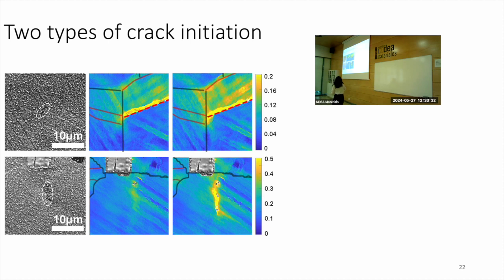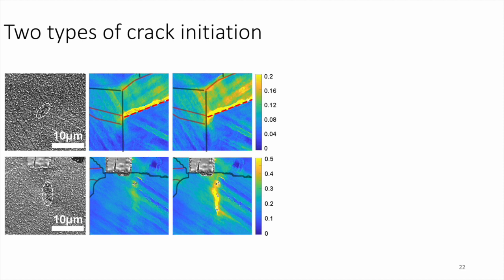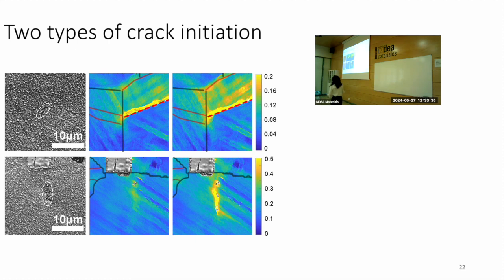In the first case, the crack initiates with localized slip, as you see in the yellow here, and this slip is actually along a CTB. This is the first type, where cracks initiate with an adjacent slipping boundary. In the second case, you can see the crack initiates inside of a grain interior, and there is no nearby slip. In the last strain image, where we know the crack has already initiated, we see this high deviatoric strain region, but this is actually due to the crack opening displacement, not a slip. This is the second type, crack initiation without nearby slip, and usually this sort of event occurs at locations where we see a surface flaw or impurity, and you see here we have a FIB mark nearby.